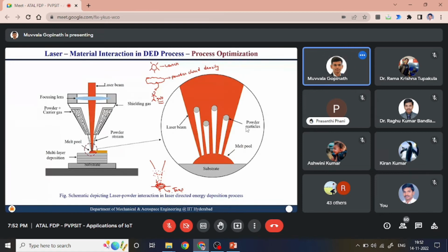Now we are talking about this trap, the molten pool on the substrate acting as a trap. Assume that this powder cloud density is too high. Then all the laser energy is blocked by this powder cloud, and the particles are just getting heated up, but they are not melting. Then you will not be able to establish this molten pool on the substrate, which acts as a trap for the incoming powder particles. So this is your substrate, and the heated powder particle will come here, carried by a carrier gas, so it has some inertia. Since it is in solid state and the substrate is in solid state, it will just deflect in this direction and that direction. So ultimately you will not see any kind of deposition.